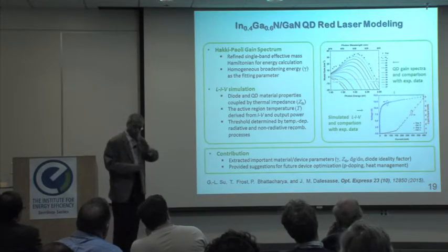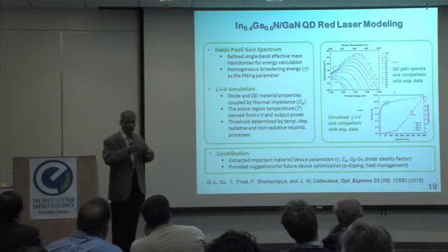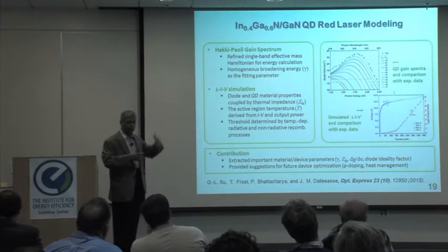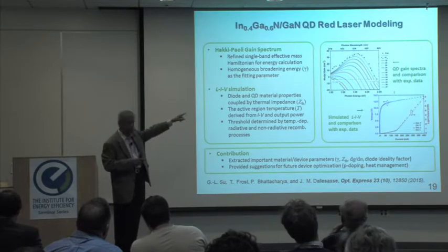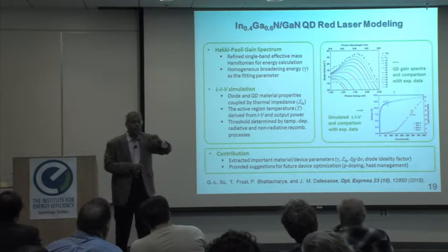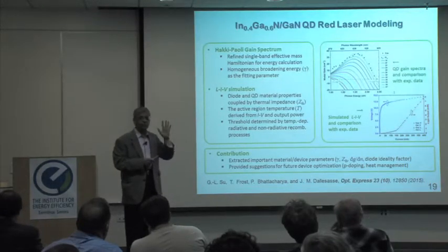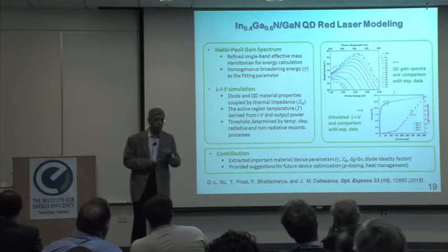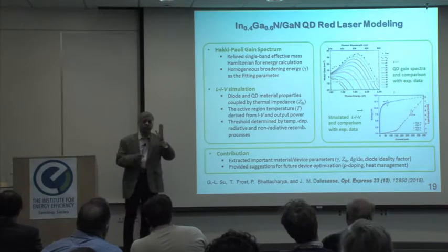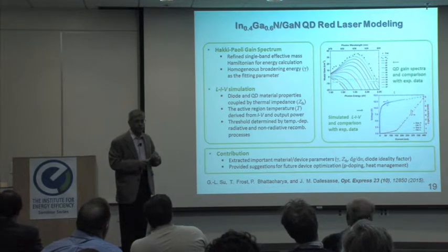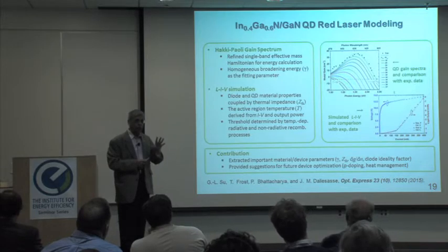Yeah, so there's a whole host of problems. One is that the devices are very hot, and the way we are measuring it, the devices are getting incredibly hot. Two, our contact technology is by no means perfect. I tell the students it's really crude. We have to learn how to make decent contacts. Three, we don't use Sumitomo substrates or anything even close to it. We are using fairly crappy substrate with 10 to the power 6 dislocations. So those are, I believe, some of the overriding reasons.